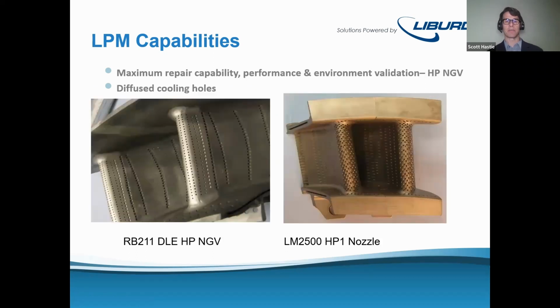So maybe I'll just stop there on the HPNGV. One thing I missed highlighting here was you can see the etched surface. We've specifically etched this so you can see the repair area on the leading edge, and that's where all those cooling holes are replaced. You can also see a repair that we do along the, these parts are originally brazed together, and after processing that braze degrades with each processing run. So we do almost a pre-repair on that surface to make sure that that doesn't become a problem in service. Less so a problem through this area, but we have seen it be a problem at the trailing edge.